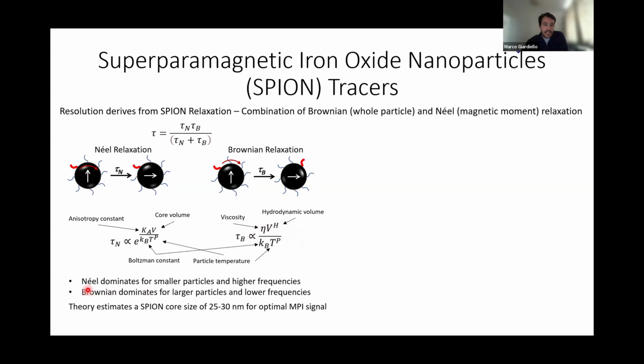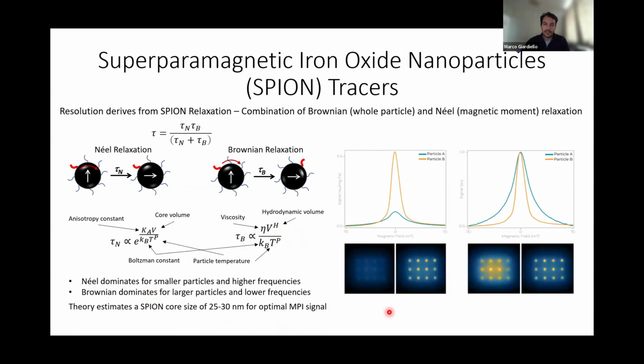In summary, Néel dominates for smaller particles at higher frequencies, and Brownian dominates for larger particles at lower frequencies, with a theoretical optimal SPION core size of about 25 to 30 nanometer. I should have put the reference for this, but it's theoretically determined to be about 25 to 30 nanometer is the ideal size of your magnetic core. And this is how these things manifest.